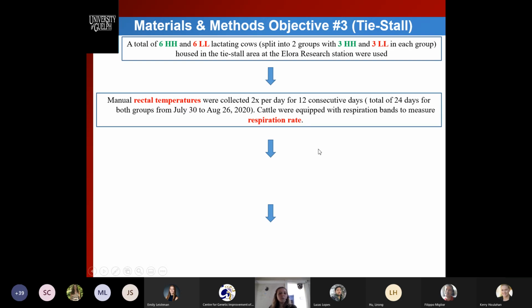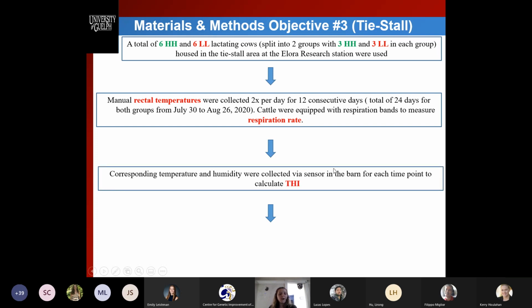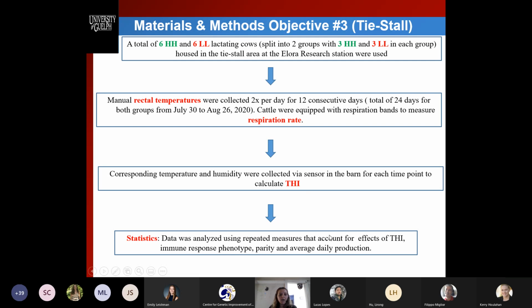And then we took manual rectal temperatures twice daily for a consecutive 12 days for each group. So in total with the 2 groups, it was over 24 days. And we did this at the end of July to the end of August. And then the cattle were also equipped with respiration bands to measure respiration rate. And then we also recorded corresponding temperature and humidity data in order to calculate temperature humidity index, and then used repeated measures to analyze this data.